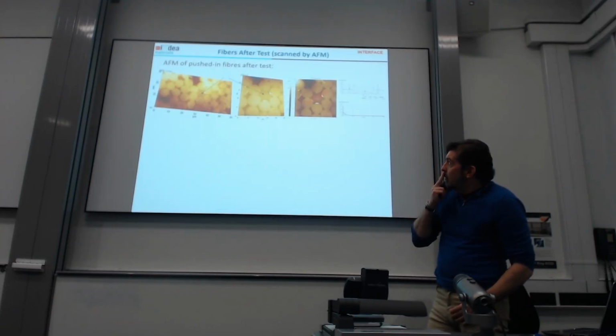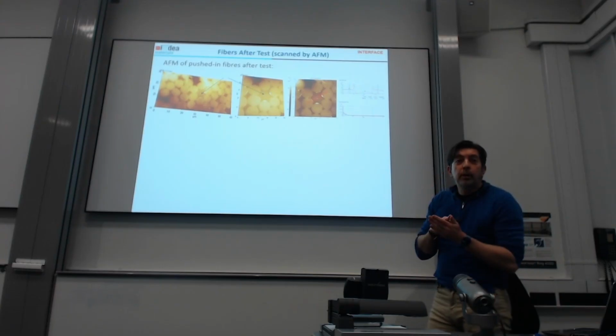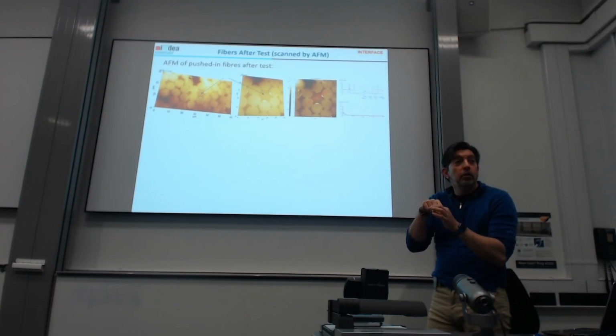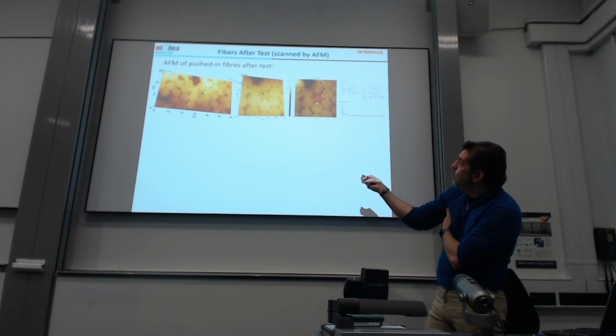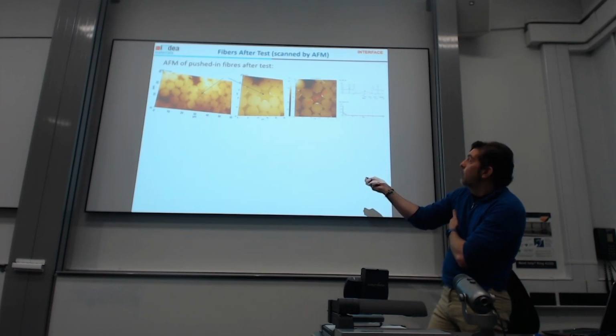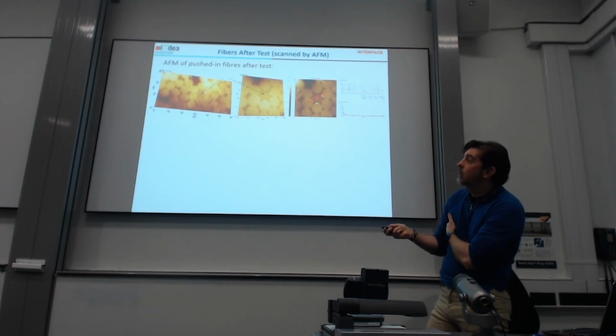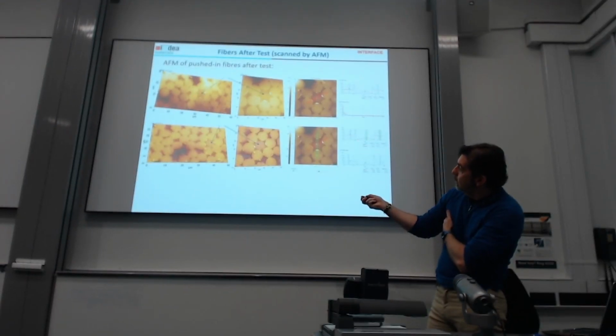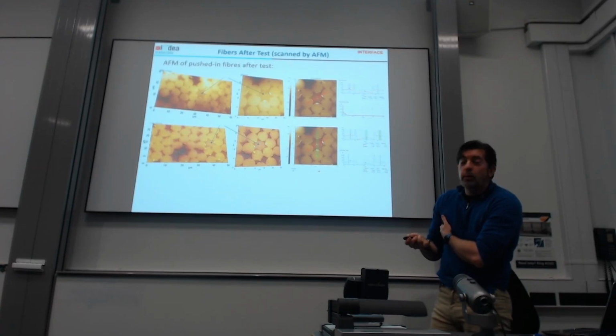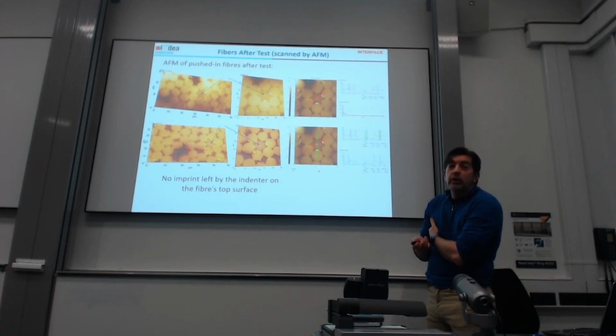In some of them, we have done some AFM just to make sure that there is no plastic deformation on the fiber. So you can see this is the pushed-in fiber in this hexagon, and we can see some pile-ups and resin coming out, but there is no residual imprint on the fiber. Okay, so this is the pushed-in fiber here, and again, no residual imprint, which is good.